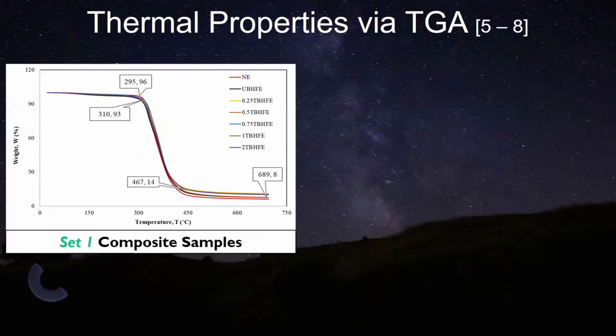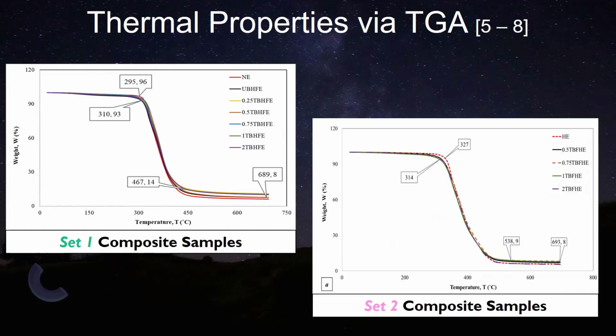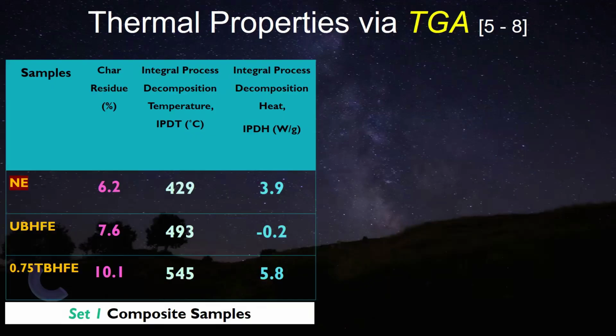And that's why when we did the thermal properties via TGA for the set 1, because it's a bit of a long list, and that is for the set 2, I will take you to the table section, which is better to represent. That's for the first set. So when it is neat epoxy for set 1, the char residue found 6.2%. Untreated, it actually enhanced to 7.6% because of the inclusion of the fiber. Because the bio-fibre has inherently higher thermal properties, which we saw before. And after the treatment, treated fiber being incorporated, it actually enhanced to 10.1%. So it's quite a good thing after inclusion of the fiber.